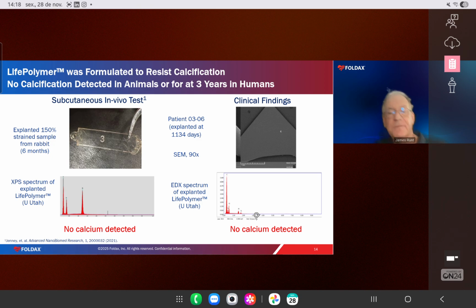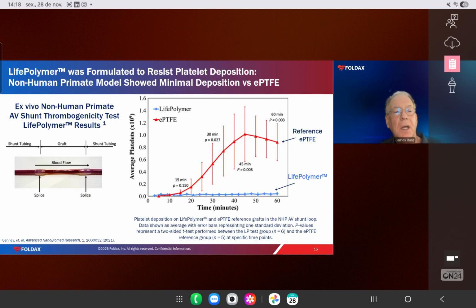So it doesn't calcify. It has good mechanical properties, and you also want it to be very resistant to platelet deposition. And so we used the non-human primate model. This was some years ago. It's also reported in that 2021 paper. What we did was use a baboon shunt model to look for thrombus formation on the LIFE polymer, and compare it to the baseline material. You can see a photograph here of the splice where the material is placed in the baboon shunt model. Again, the details are shown below in lower font.